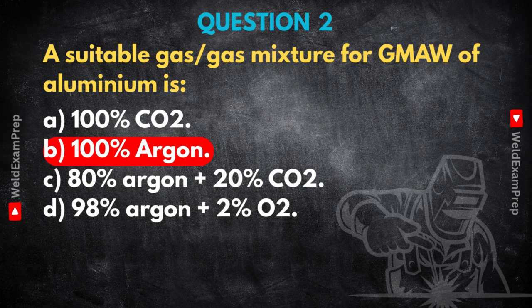Now, if you were to use those other options like A, C, or D, which contain CO2 or oxygen, well, they would react. Bad news for aluminium. Very bad news. You'd get significant oxidation, probably lots of porosity, little gas bubbles trapped in the weld, and that just kills the weld's strength and integrity. So for aluminium GMAW, pure argon is the standard. Right, that inert property is key. Non-negotiable for a clean aluminium weld.